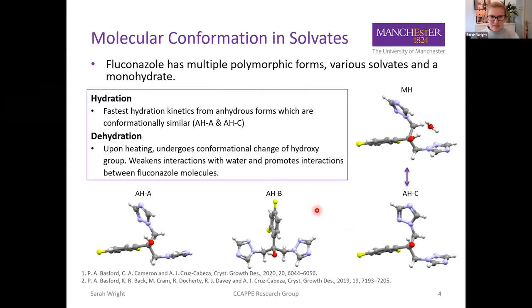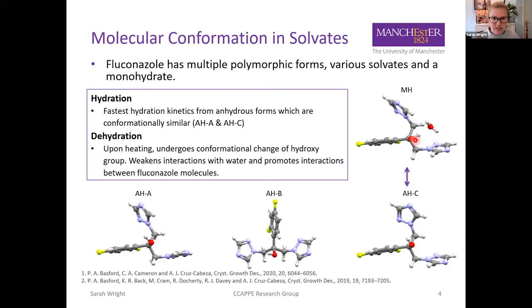An example where conformation and solvates have been studied together is Pat Basford's recent work on the impact of conformation on the hydration and dehydration mechanisms of fluconazole. Pat found that the fastest hydration kinetics are observed from the anhydrous forms which are conformationally similar to the monohydrate — anhydrous A and anhydrous C. Upon heating of the monohydrate, there is a conformational change of the hydroxy group which weakens interactions with water and promotes interactions between the fluconazole molecules. The fluconazole monohydrate also dehydrates to anhydrous C, which is conformationally similar to the monohydrate.